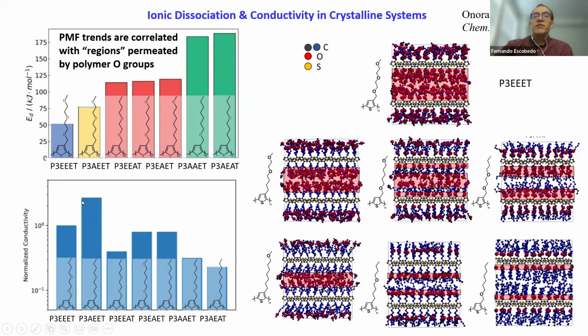Now, in this case, you find that, in fact, the second system, the one that has only 2 oxygens near the chain end, was in fact somewhat better than the base system. And one reason that we came to understand is that the oxygen which is too close to the thiophene ring is the less mobile of them. So if the lithium ion tends to be associated with that oxygen, in some ways that's going to slow it down somewhat. So at the end, even though that system has a slightly higher barrier, so it's harder to dissociate, when it comes to the mean square displacement, it tends to move better than the canonical system. So that was interesting.